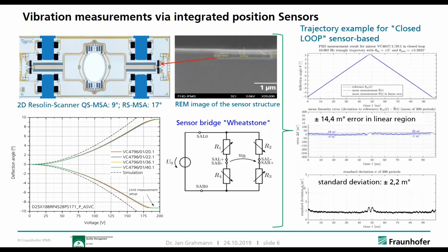And here on the right side, you can see a few results. So for a triangular trajectory, in this case of the quasi-static axis, we achieved in closed loop, so using the sensor signal in order to drive the quasi-static scanner more precisely in its trajectory, in order to minimize the error between the actual linear trajectory and the deviation seen.